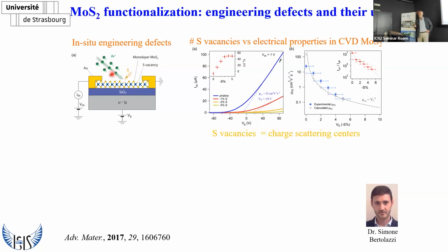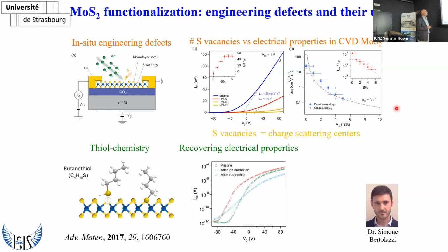Of course, this means that from the electronic point of view, the material gets poorer and poorer. You can see here that increasing the number of sulfur vacancies, the electron mobility exponentially decreases, because sulfur vacancies are scattering centers for the charge transport. But it is known that sulfur vacancies can also be healed by thiolated molecules. So here we took a very basic, commercially available thiolated molecule and used it to heal these vacancies. This is the initial IV characteristic, this is the one after the ion bombardment, and then we recovered to a great extent the initial IV characteristic upon butanethiol treatment.